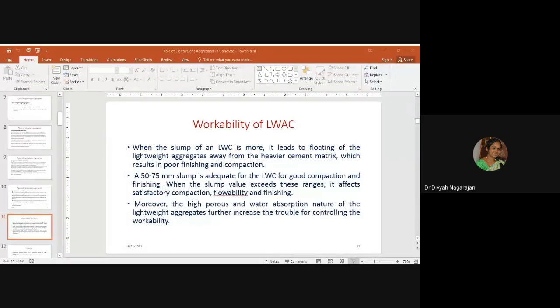But previous studies mentioned that the split tensile strength and flexural strength are either comparable or superior to normal aggregate concretes. This solely depends upon the origin or place where the aggregates were produced, or the admixtures used for the production of the lightweight aggregates and also the concrete. The split tensile strength and flexural strength of lightweight concrete can be directly correlated to the compressive strength.